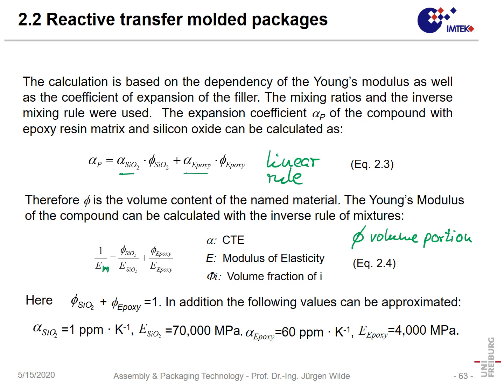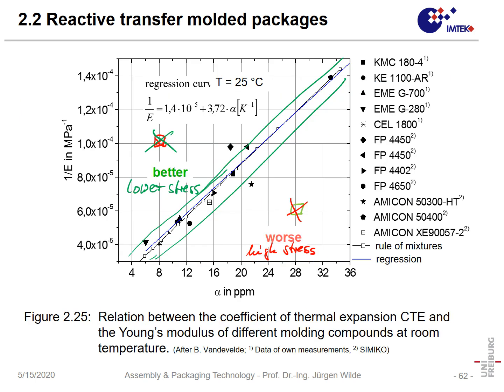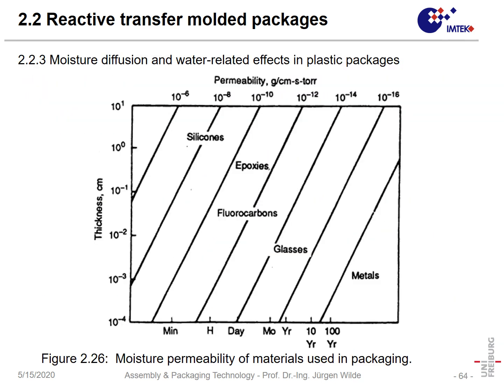Okay, in that way, we have seen the rule of mixtures, and in fact, when we go back one slide, one of the curves here is the regression curve, that's the blue one. On the other hand, we took the data of the resin and of the silicon oxide, and we computed, based on the rule of mixtures, this other curve, and we can see the model is very similar to the regression, and that is a good indicator that our model described by the rule of mixtures is valid. So in that way, we have a materials modeling, which is very useful for our investigation, and one thing which is also important is that this master curve prevents us from desiring materials which can never exist.